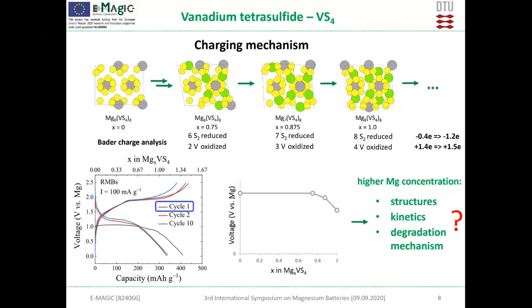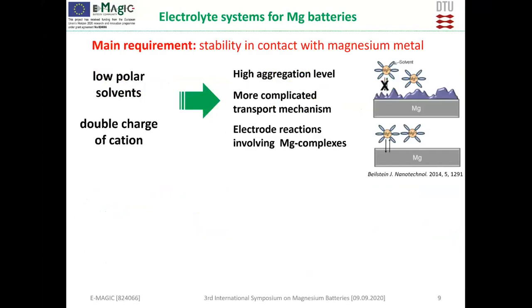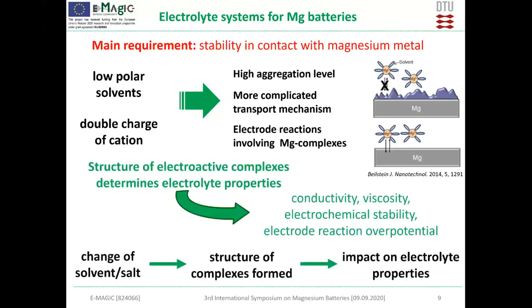So switching now to electrolytes. So far, the requirements for the electrolytes are that electrolytes should be stable with a metallic anode, to prevent any formation of a passivation film that could prevent the ionic transport between electrolyte and magnesium. Because of that, we usually use low polar solvents, and that together with the double charge of the cation causes huge aggregation of the system and formation of clusters. And indeed, these clusters are responsible for most of the properties of the electrolyte. So if we want to study the change of the solvent or salt and look at the impact on the electrolyte properties, we need to find out what is the structure of these complexes.